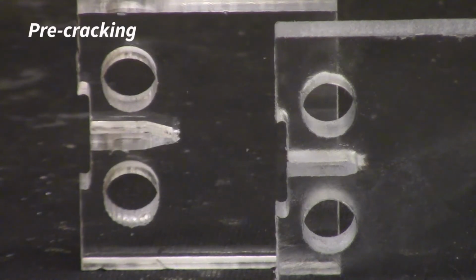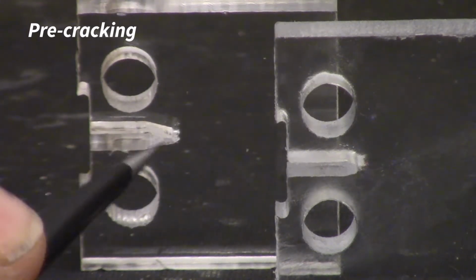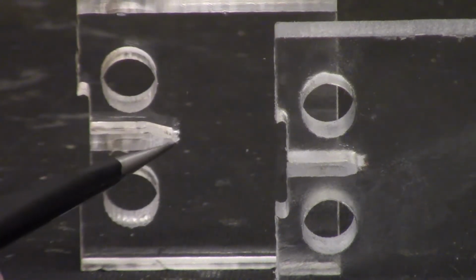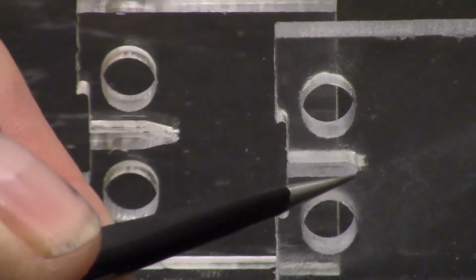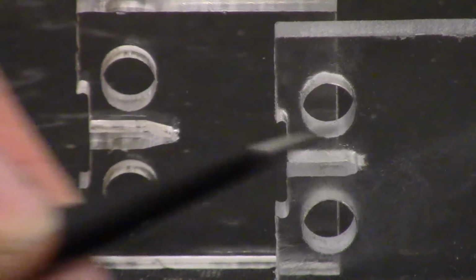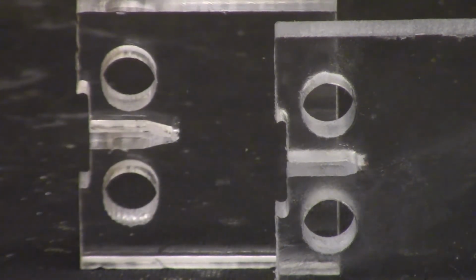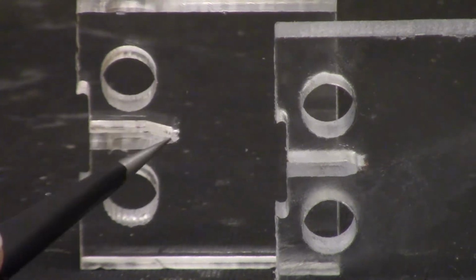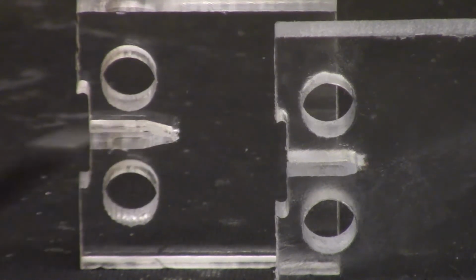So part of the specimen preparation is to create a pre-crack. So for the plastic specimens, you can see that we've already done that. You can see these pre-cracks here at the root of the notch. The notch is machined in where we remove material. The pre-crack needs to be made in such a way that no material is removed, and we just have a clean crack separating the upper and lower part of the specimen.